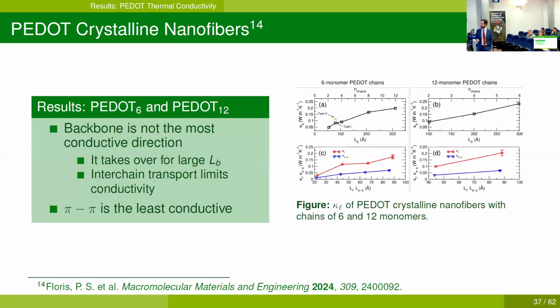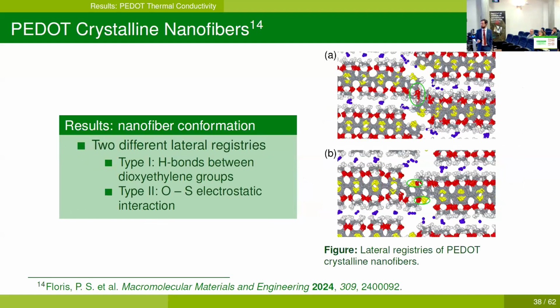Yes, I forgot to mention, you see I put two arrows here, type 1 and type 2. So this refers to how the nanofibers can arrange along the backbone. So we see type 1, we refer to H bonds between dioxyethylene groups of the terminal monomers of different chains. And you see there's this sort of S behavior. Whereas type 2 is a little bit different, and it's an oxygen-sulfur electrostatic interaction, also between terminal monomers of different